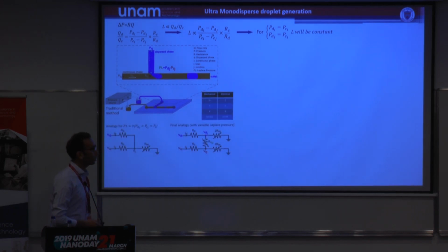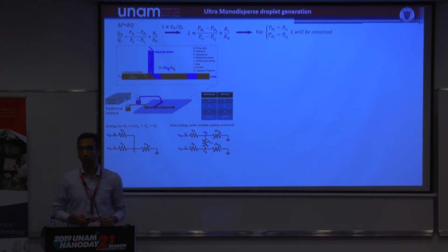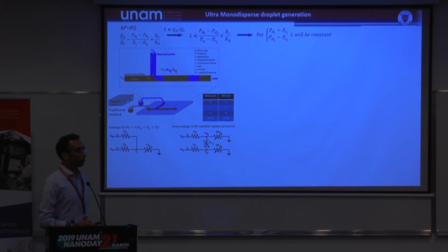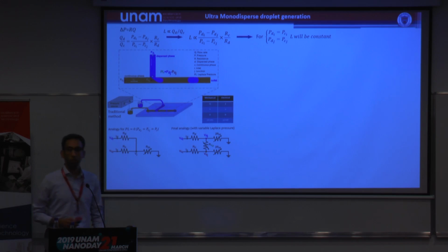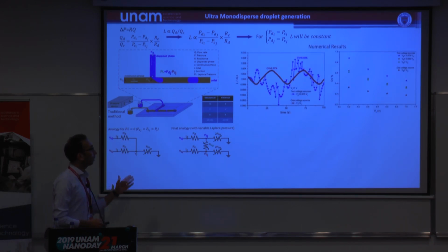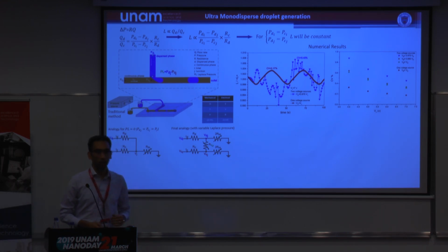Normally, people use a pressure pump in order to make droplets. We propose a method in which we can make ultra-monodispersed droplets by using a single port of the pressure pump and supplying identical pressure. We made an analogy and did a simulation based on that analogy between mechanical and electrical components. We got this result that shows when we supply identical pressure from a single port, we can have a better CV. CV shows the coefficient of variation of droplet sizes. So when we increase that identical pressure, we can have better monodispersity for droplets.